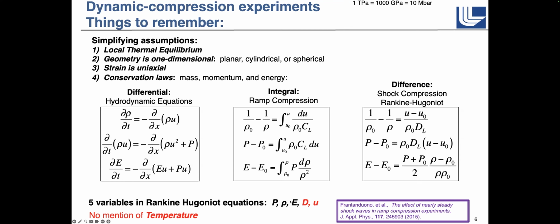And you notice here that there are 5 variables in the Rankine-Hugoniot equations. There's the pressure, the density, the internal energy, and in shock compression, the shock velocity. In ramp compression, it's the sound velocity and the particle velocity, the speed at which the particles are moving after the shock or the ramp moves through. There's no mention of temperature. And that's one of the big issues with dynamic experiments, that it's extremely difficult to measure temperature.